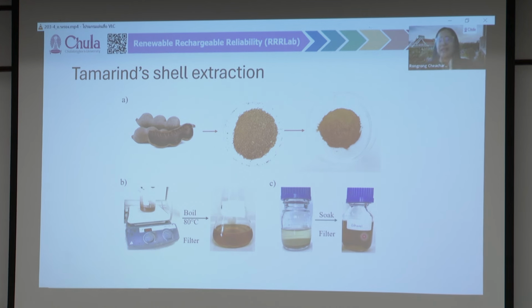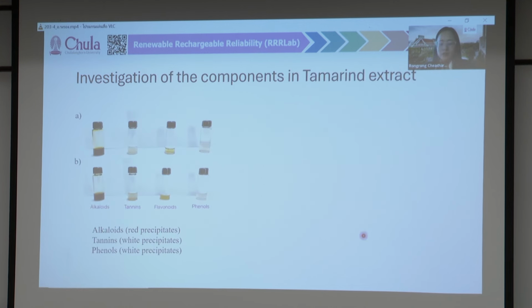So we think that if we want both the potassium and the organics, we should probably go with the water-based extract. So we take the water extract and go further into the synthesis. But first, we do the phytochemical testing of the water extract and the ethanol extract of the tamarind shell. It's quite similar: even though the amount of potassium is different, in both cases we found alkaloids, tannins, and phenols.